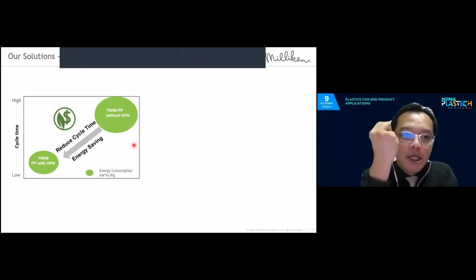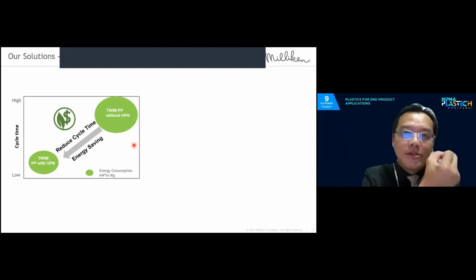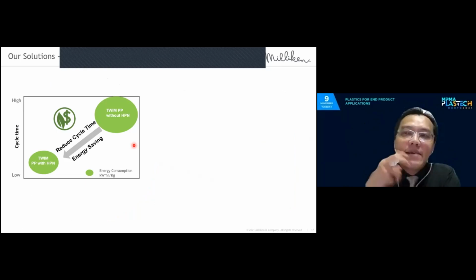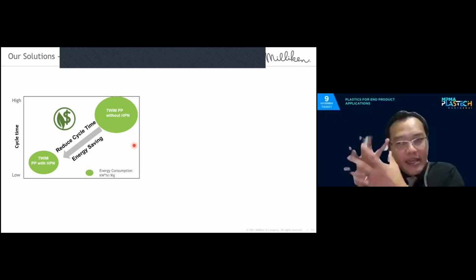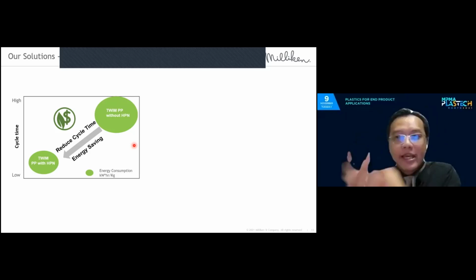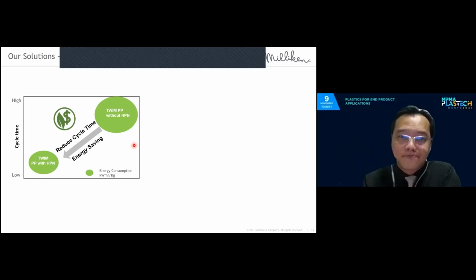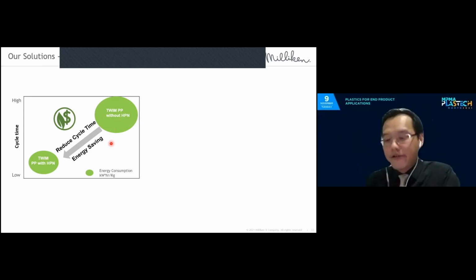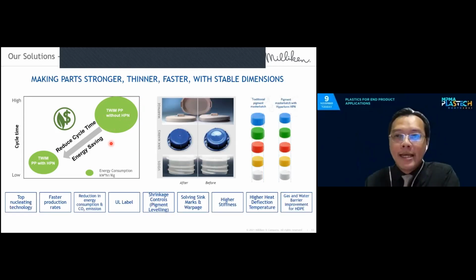HPN, Hyperform, nucleating agent. What it means is that when it is injected into the mold, it enables a more efficient nucleation and crystallization of the PP, and therefore it solidifies, it sets quicker and faster in the mold compared to a polypropylene without HPN. And again, all the data suggests on average 5 to 8%.